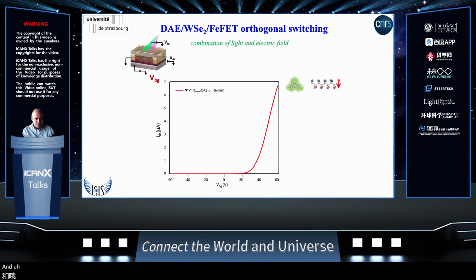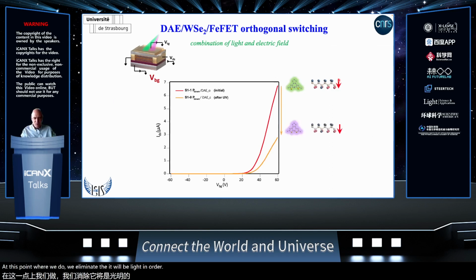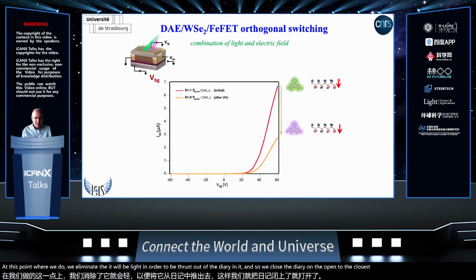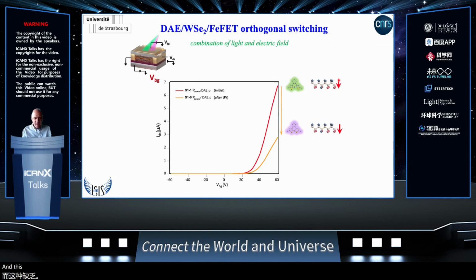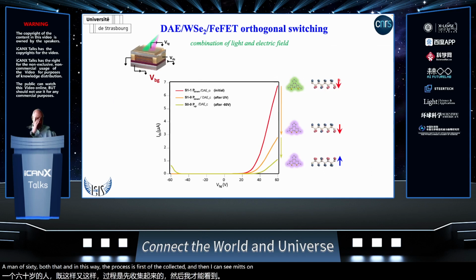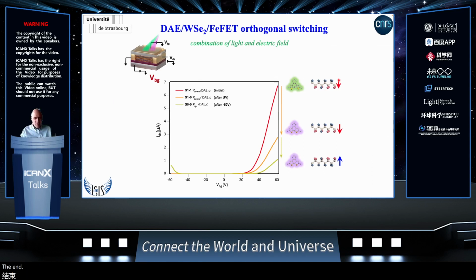And at this point, what we do, we illuminate with UV light in order to create traps out of the diarylethene. And so we close the diarylethene from the open to the closed state. And this is accompanied by electron trapping and decreasing the current through the junction. At this point, we can further decrease the current by applying a minus 60 volt. And in this way, the channel is further depleted of electrons, and we reach the lowest current possible, that is obtained by diarylethene in the closed state and P up.